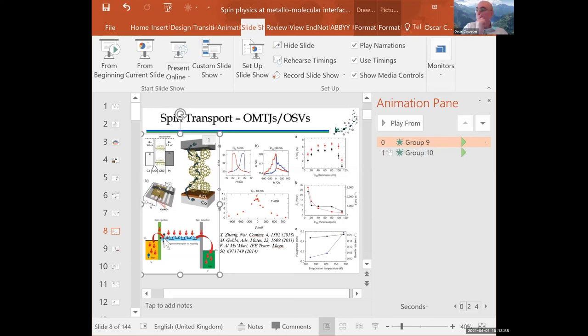I don't know if you're familiar with variable range hopping, but it's a very small tunneling of just an angstrom or a few angstroms each. In each of these hopping steps, there is a chance that the spin will flip because of thermal fluctuations. So the more hops, the more chances that your electron is going to depolarize before it arrives at the other electrode. However, because the spin-orbit coupling is very small and the hyperfine interaction is also small, at least in C60, you can have many hops before statistically your spin is going to flip.